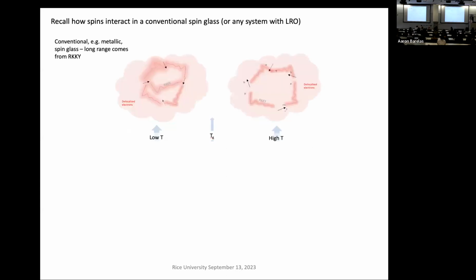How does this work? Well, in copper manganese, in canonical spin glasses, you have an interaction. It exists independent of whether the spins are there or not. It sort of kicks into action when you put spins in, but the conduction electrons are there. And when you see freezing, it's a competition between the average strength of that interaction and the thermal energy. When the thermal energy becomes less than the interaction energy, then you see some sort of freezing.